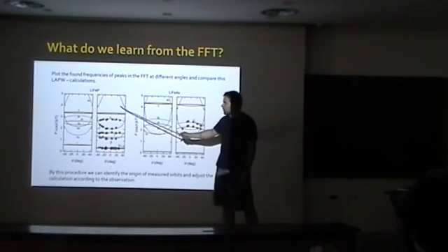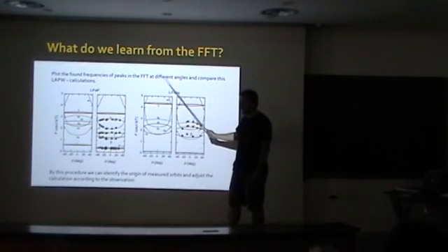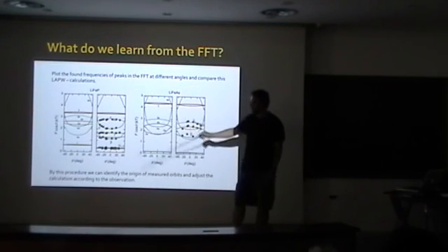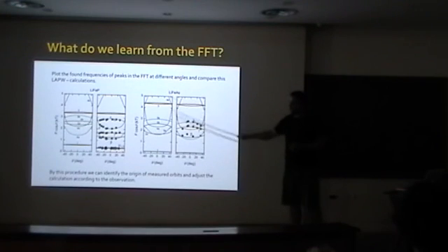So that's why we're working on getting cleaner samples, redoing that, and also maybe going to higher fields, where, with the mean-free path, we might be able to have those oscillations grow out. But this is a problem, and this is why in most materials it takes quite a long time to see quantum oscillations, because we're limited by the mean-free path. And because those two are stoichiometric, we were lucky to see it quite fast.